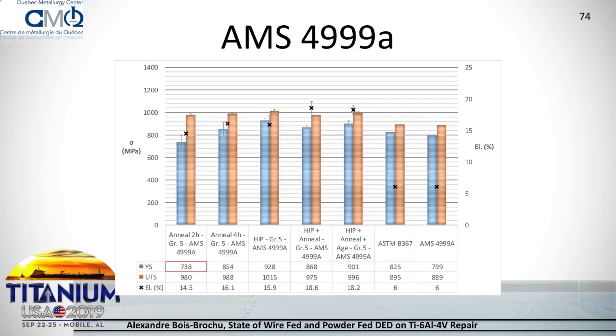So here you can see the results for the various heat treatments, the evolution of mechanical properties, and you can see that the requirement of AMS 4999A is quite small, 800 MPa. And if you do an annealing at 915 for 2 hours at this temperature, even with grade 5, you won't reach the yield strength required by the standard. And this is even below the requirement from ASTM B367, which is 825. And it gets worse if you look at grade 23.